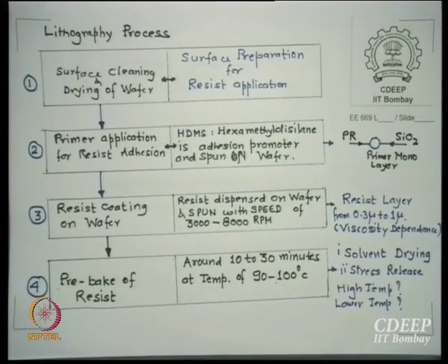Normally this is run in a little higher temperature oven, and the oven is running with a huge amount of nitrogen flow inside. Typical flow in normal ovens is around a few liters per minute, but we need roughly at least 30 liters per minute flow inside the oven chambers, so that there is no oxidation of wafers and no dust going onto it. Sometimes we may even put the wafer in the furnace and take it out, but if there is a metal, don't put it into the furnace. If it is oxide, nitride or anything, yes, you can push it in for drying in the heated furnace at the edge, and nitrogen is anyway passing through. So you can put it there for a while and then take it for masking.